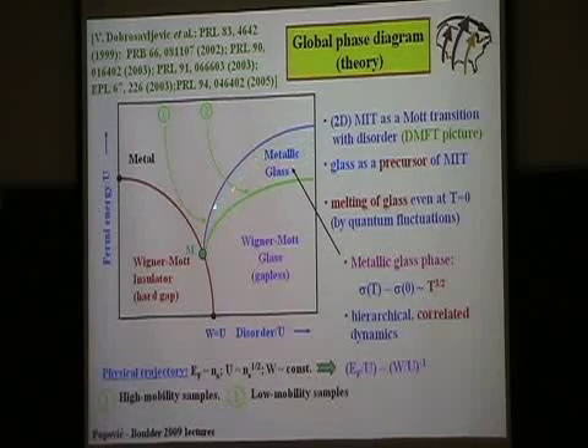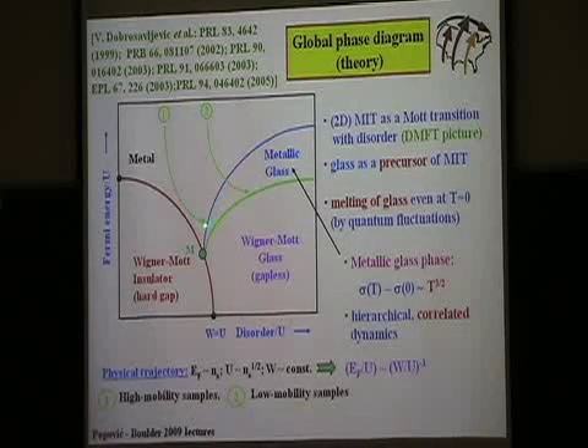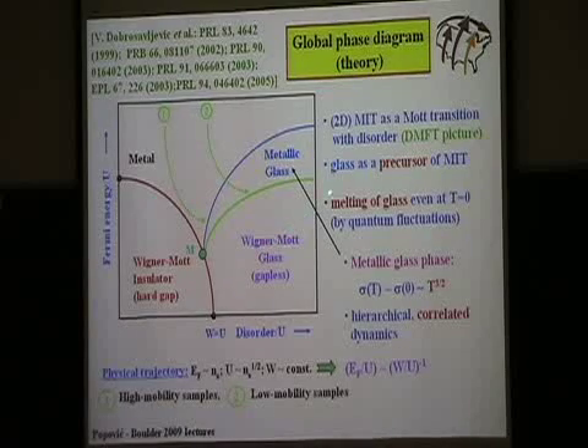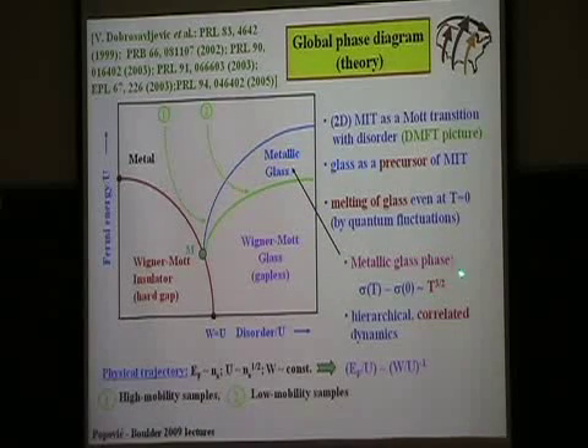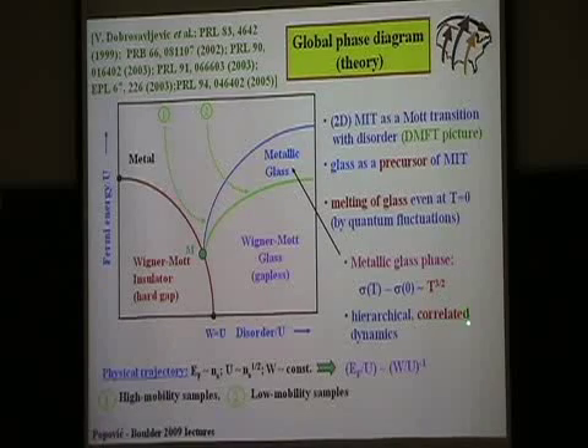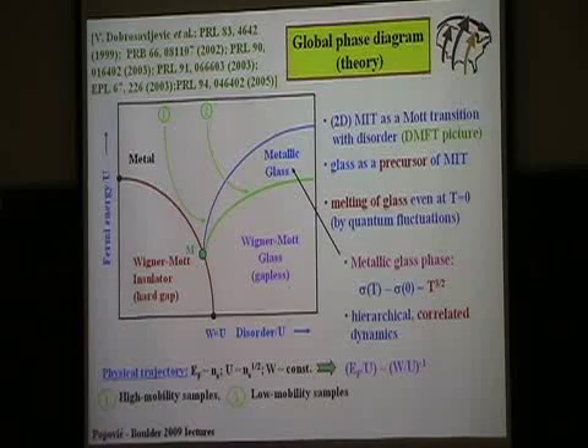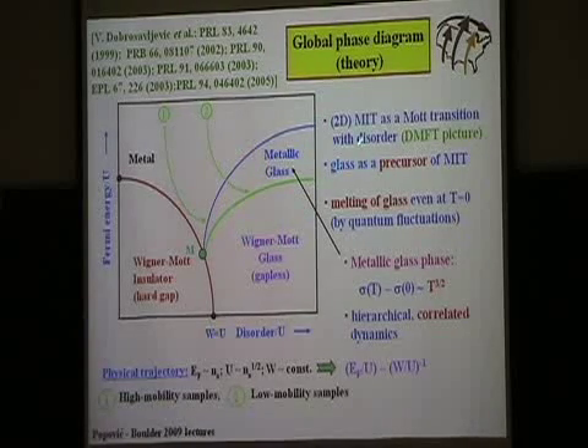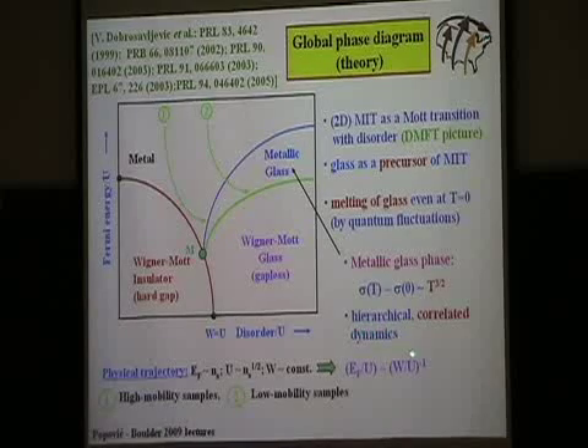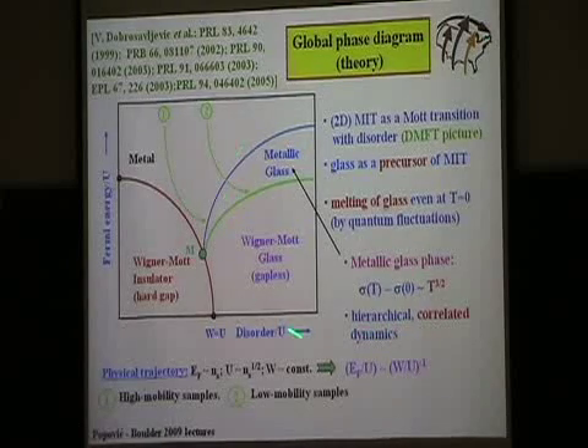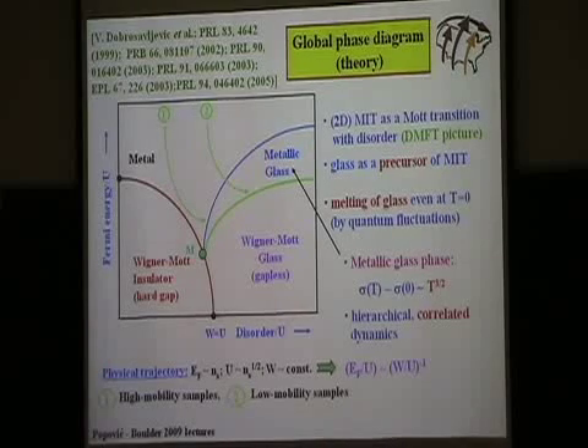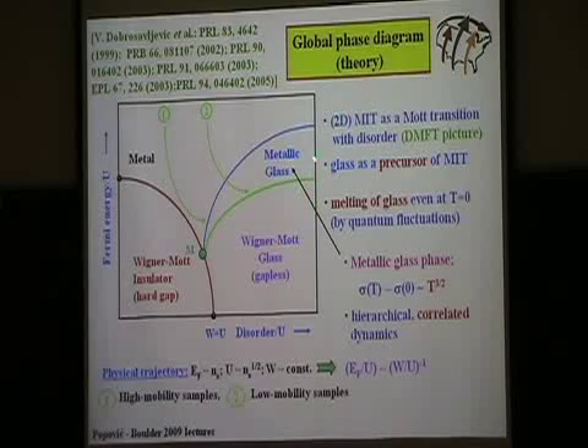So the existence of this intermediate phase, its dependence on the disorder, are consistent with what we found in the experiment. Also, for this intermediate phase, as I mentioned yesterday, they find the same temperature dependence that we found, and the type of model that they used to obtain this phase diagram is known to produce hierarchical dynamics for glasses. So the main features are consistent with what we have found. And this phase diagram is independent of the dimensionality, so this is expected in both 2D and 3D.